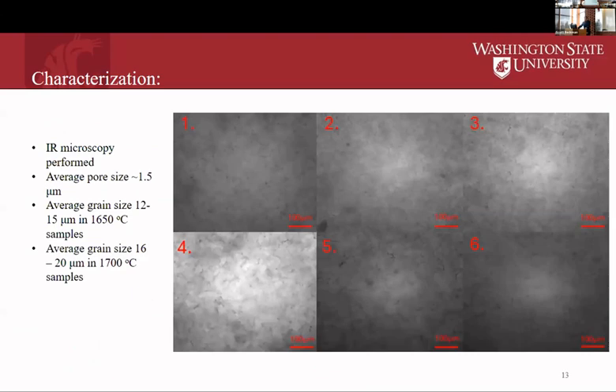You can see in these IR microscope images that we took both the difference in grain size between samples sintered at 1650 degrees C and those sintered at 1700 degrees C.